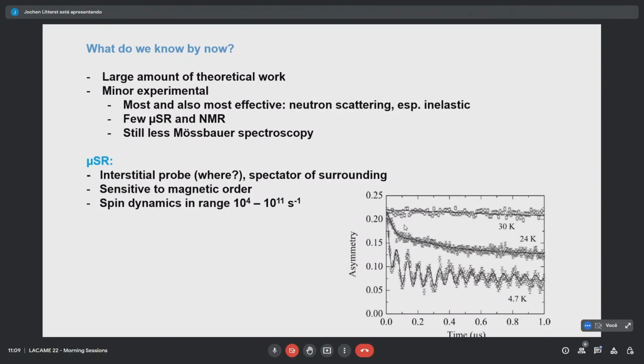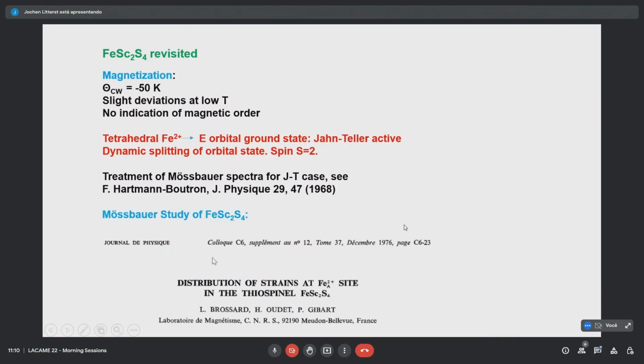If you are not magnetic, you simply will see a simple damping. And the damping reflects the spin fluctuations, and especially the spin fluctuation frequencies. The stronger it's damped, the lower are the spin correlations. And with that, we can probe if a material is slowing down or speeding up in the fluctuation frequencies of the spins. Let me turn to this example I had promised, iron scandium sulfide. It has been studied several times before.